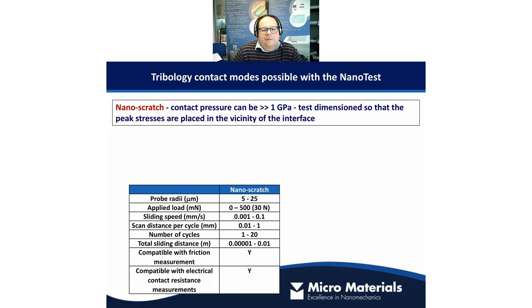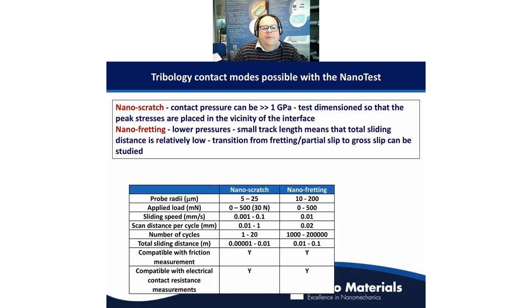So next slide. Another technique is nano fretting. So fretting is a lower pressure test, okay? Still a small track length, okay? But many cycles. So where scratch testing was 1 to 20 cycles, we can be talking about 1,000 to 200,000 or more cycles in a fretting test, but a small amplitude. So here we're talking about up to about 20 microns.